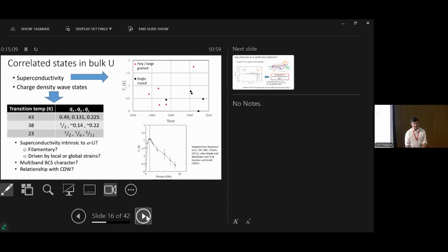Okay, but let's talk about uranium. It's a heavy element, heaviest naturally occurring element. It's a superconductor, maybe. It's a bit controversial. So it's been known for about 70 years, but actually the superconducting transition jumps all over the place. And this one down here with 0 TC is the cleanest crystal. So the best crystal is not superconducting. So that's kind of interesting. It also shows charge density wave states.